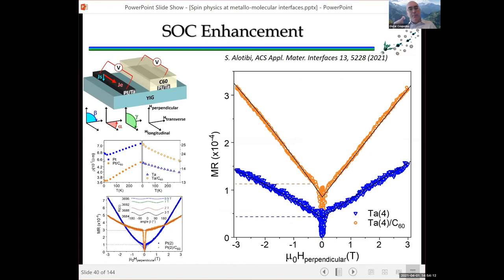The difference is many people do spin Hall magnetoresistive measurements at large magnetic fields. That is very dangerous because you are starting to merge the spin Hall magnetoresistance with other effects like ordinary magnetoresistance, Hanle effect, localization, thin film magnetoresistance. And those effects are also affected by the molecular layer, but differently in tantalum and platinum. In tantalum, those effects at large magnetic fields are enhanced by the C60. In platinum, those effects are reduced, but in both cases, the spin Hall magnetoresistance is enhanced.